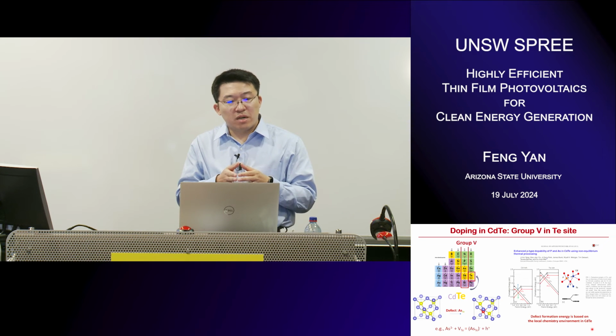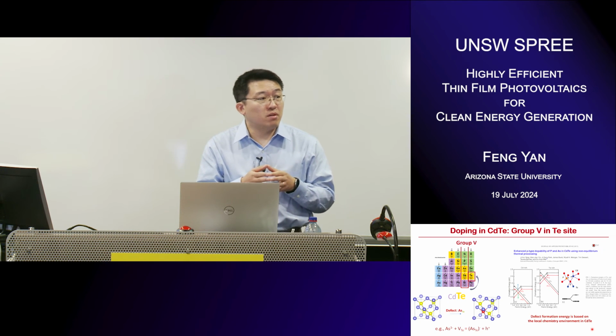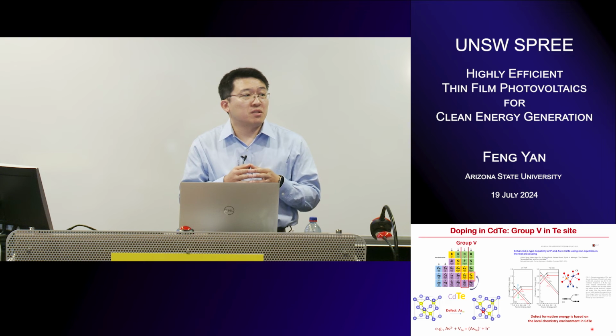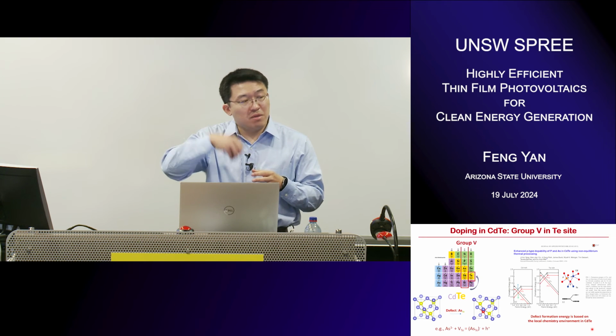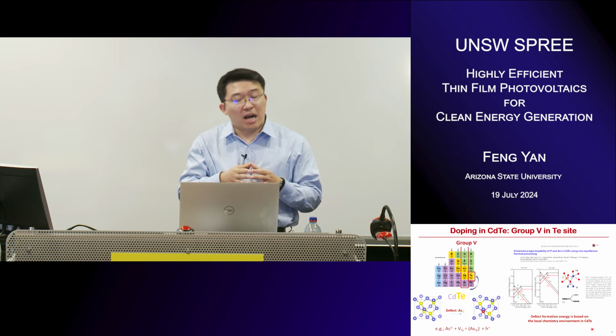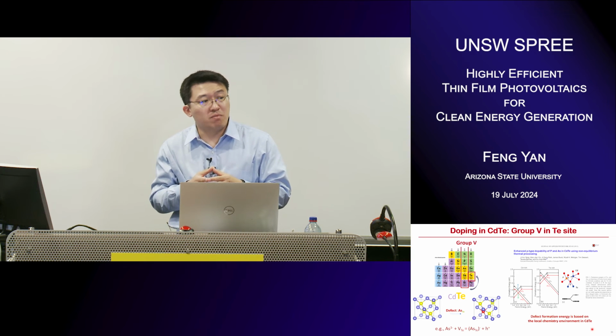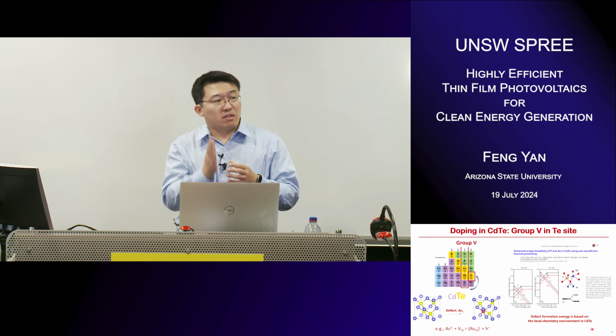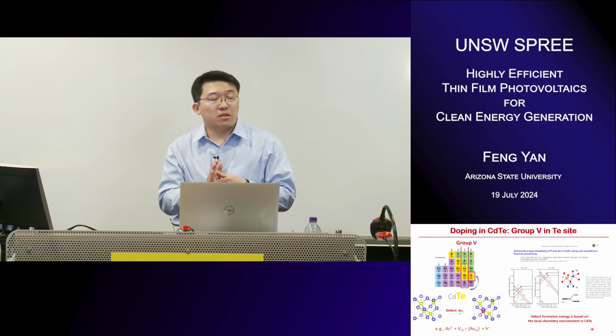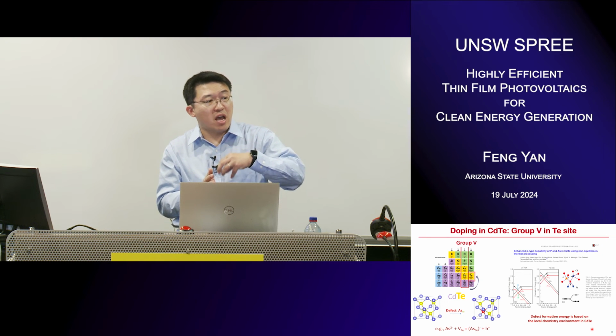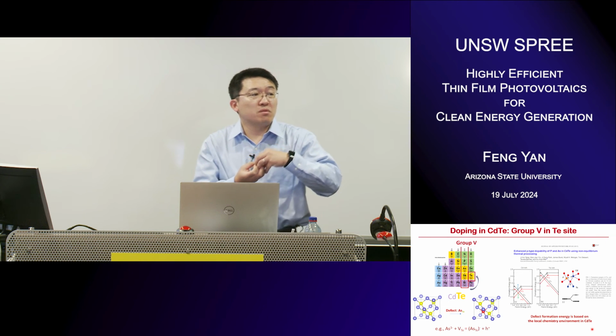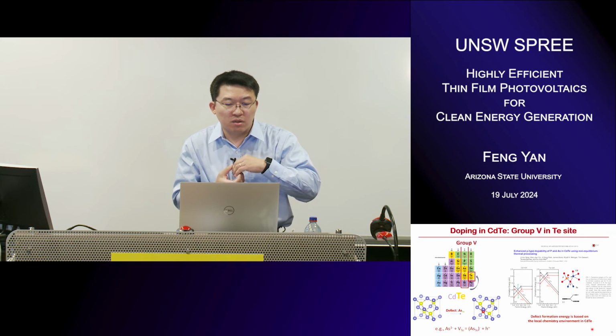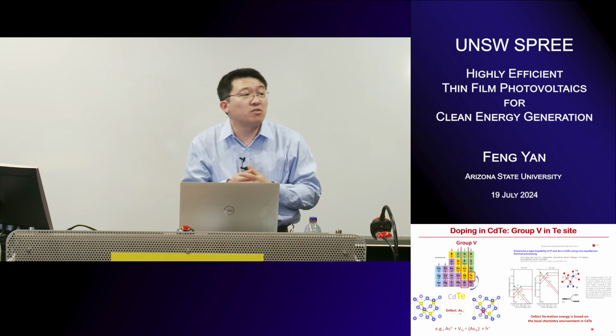For example, the grain boundary is relatively cadmium poor, or cadmium rich, because more cadmium is introduced inside. After the cadmium chloride treatment, the chlorine segregates at the grain boundary, and then when the dopant is introduced, it is probably easier to hold it in the grain boundary than to further diffuse into the grain interior. Yeah.